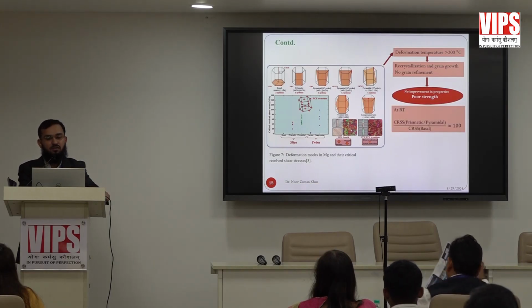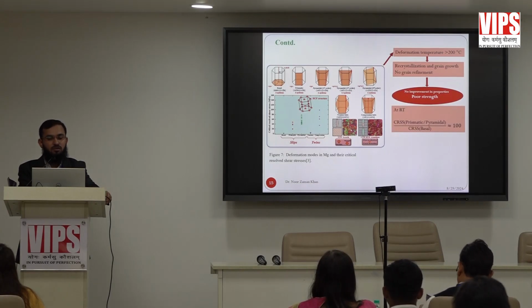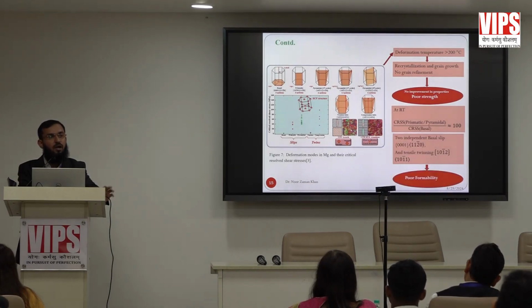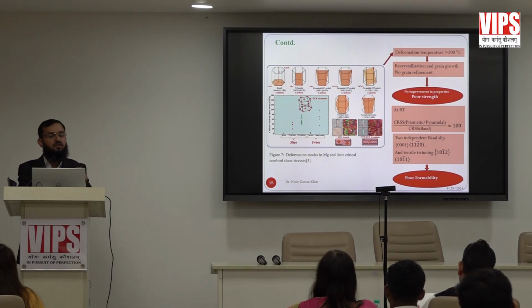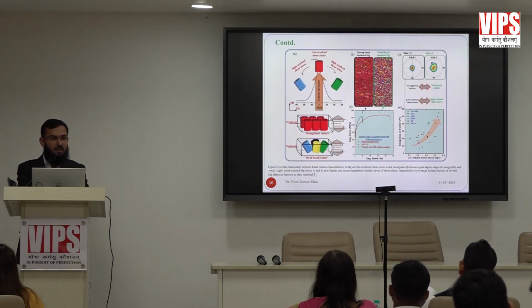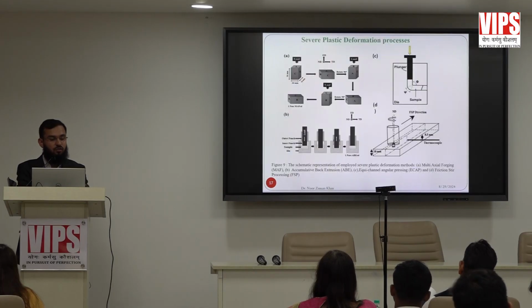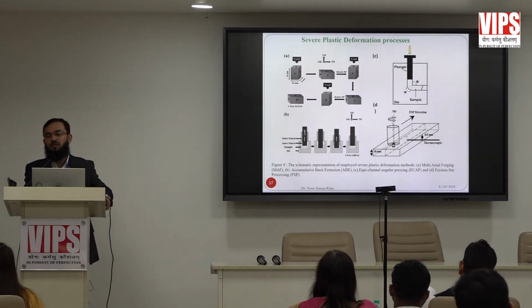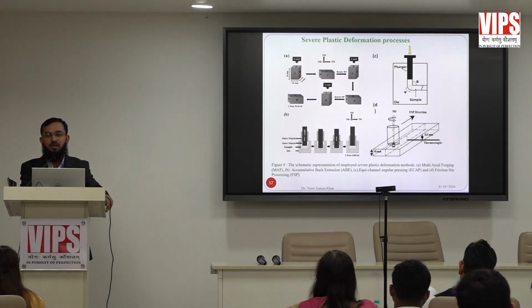So it will lead to poor strength. If it is poor strength, there is a term which is critical resolved shear stress. So ultimately magnesium has poor strength and poor formability even after alloying. So what could be the possible solution? Again, texture. We can improve the strength, minimize the texture, and enhance the texture weakening.